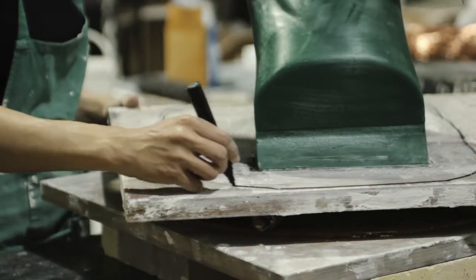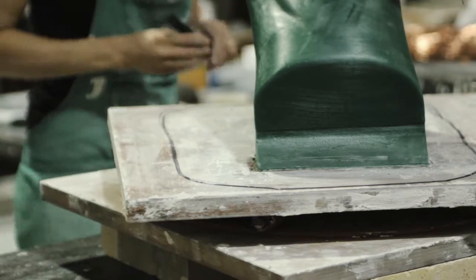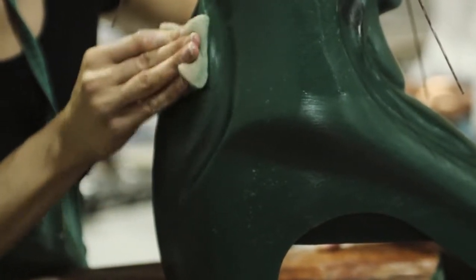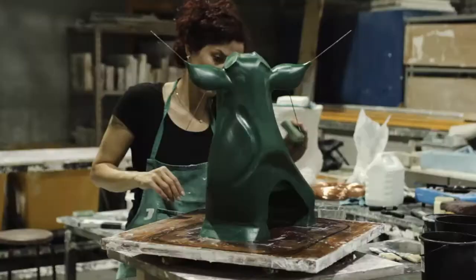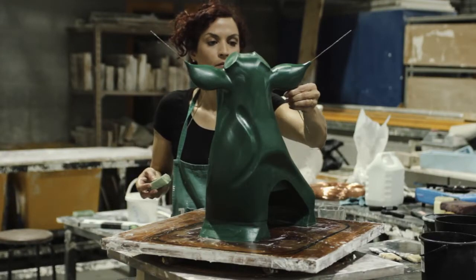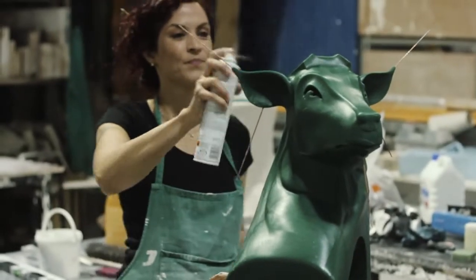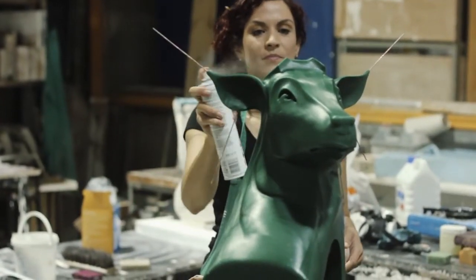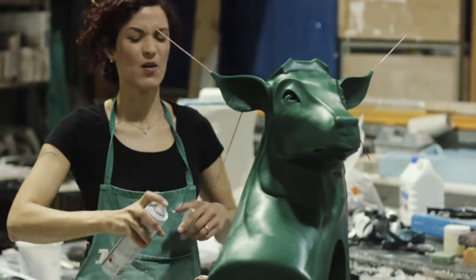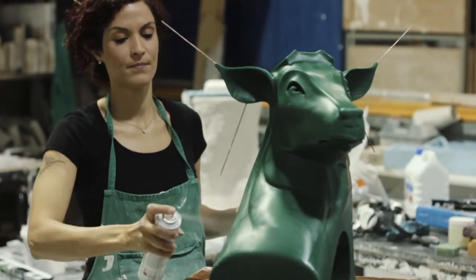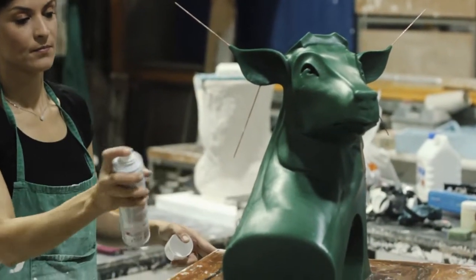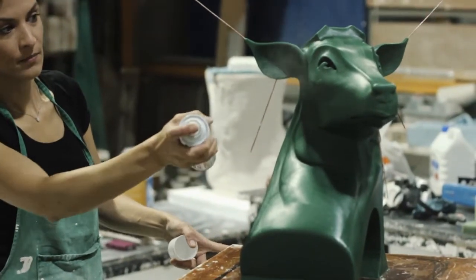Just before I start working on the refractory mold, I take the wax, because I don't normally use turpentine to smooth the surface of the wax, so the plaster doesn't stick, it just runs off the model. What I normally do is take a hairspray and spray the whole wax model with hairspray, let it dry for about 2 or 3 minutes, and then I can start making the face coat.